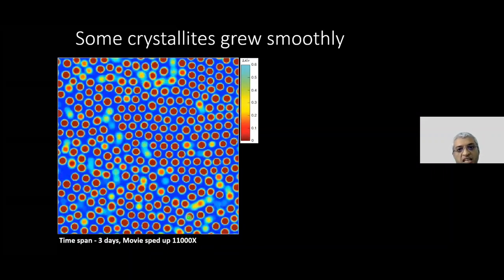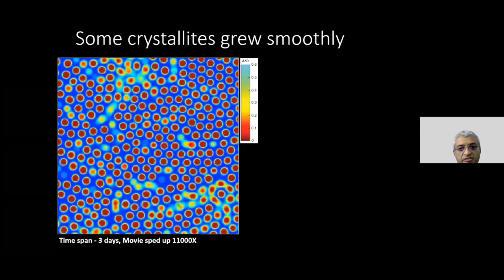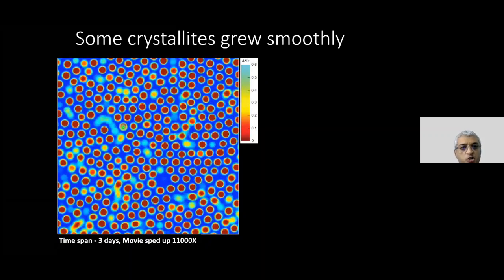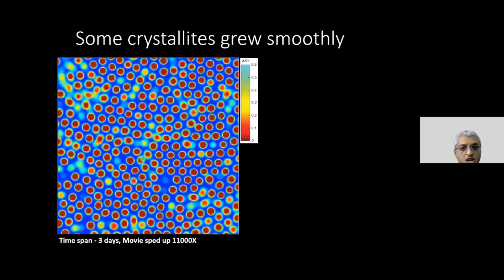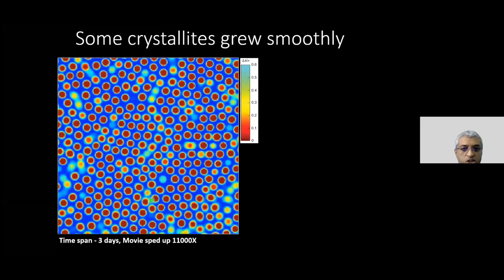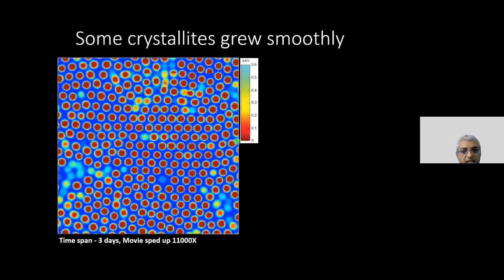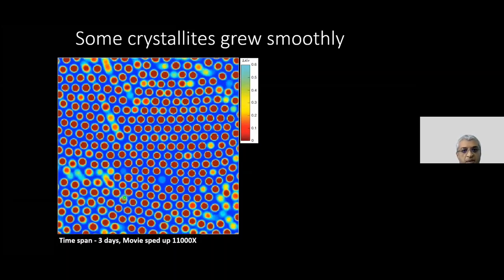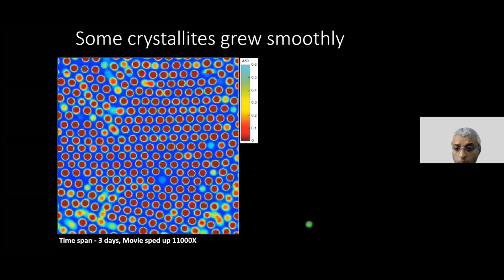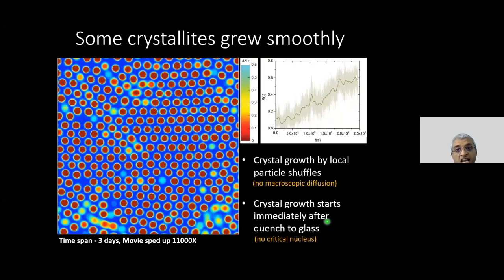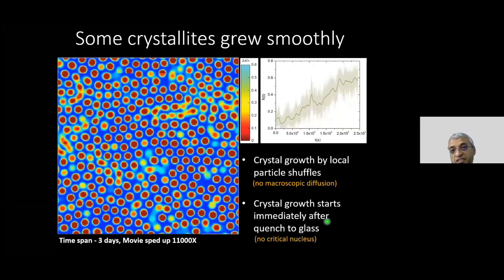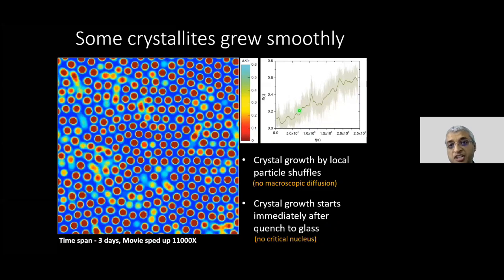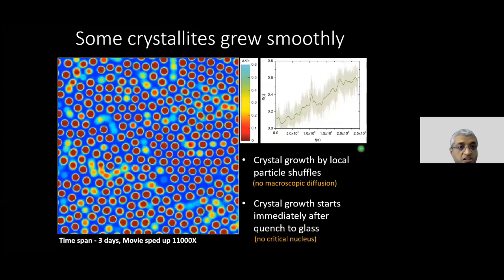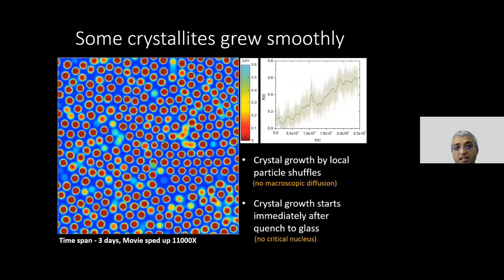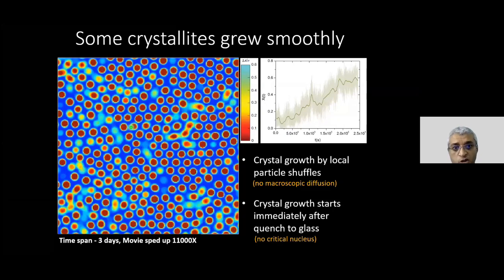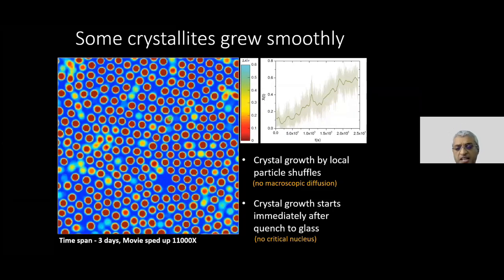and what you will see are these sort of displacements in which no single particle makes a large move, but there is a collection of particles which make these short moves, and at the end of the day, you have this nice, beautiful crystalline patch, okay, which is just visible. All right. And now I can plot the x of t for this particle. And the first thing that you see is that crystal growth, like I said, is by local particle shuffles. There is no macroscopic diffusion of any particle, which is forbidden because I'm in a glass.